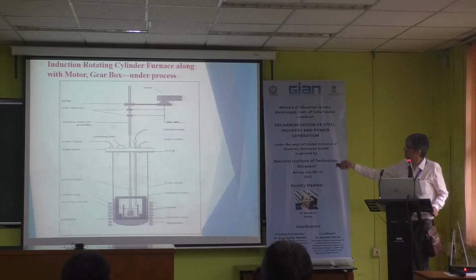This could be rotated at various RPM, and the sample of the melt pool could be collected at certain time intervals, so you can understand the dissolution, for example, the lime dissolution in slag. One can have a lime cylindrical sample fitted on the cylinder, dipped into the already melted slag and rotated at various RPM. These kinds of experiments have taken place earlier, but now also the dissolution of graphite into iron melt could be done.